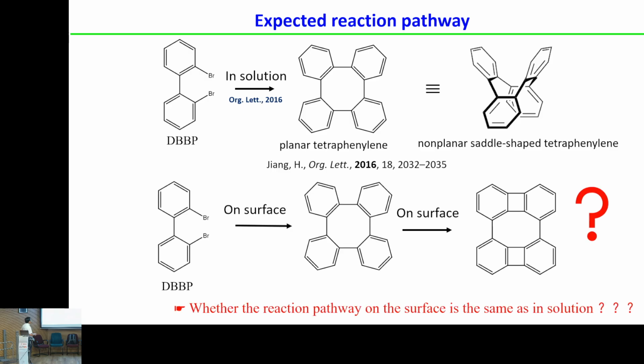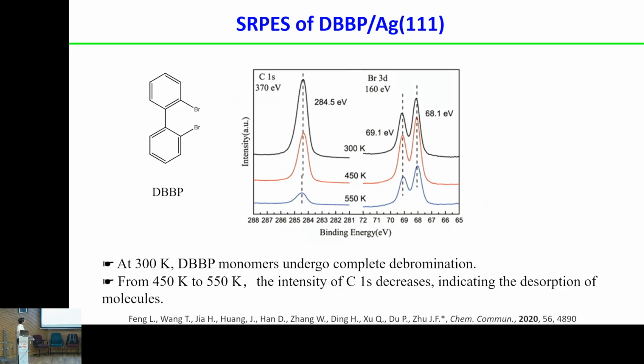On the surfaces, we think whether it's possible to form this same structure, but planar, and then if you further heat the temperature, it will form this structure. So this synchrotron radiation photoemission tells us that if you put this precursor molecule on silver 111, debromination reactions immediately start. And if you further increase the temperature, you see that the intensity drops. That means that you also have a desorption of these molecules with increased temperature.